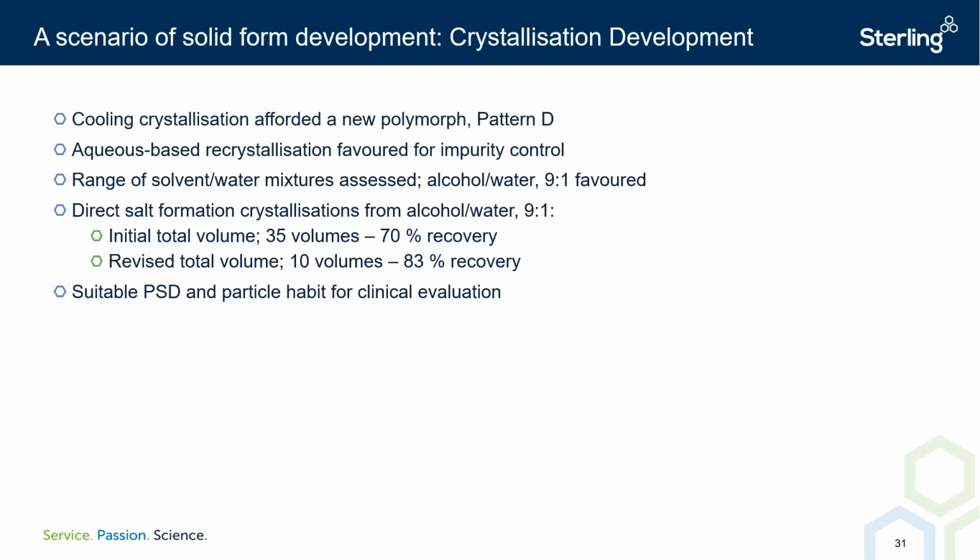Following a few iterations, a reactive salt formation was devised that afforded the target API salt version with desirable characteristics, including suitable particle size distribution and particle habit for clinical evaluation, and an 83% recovery that performed well during GMP manufacture on a 4 kg scale.